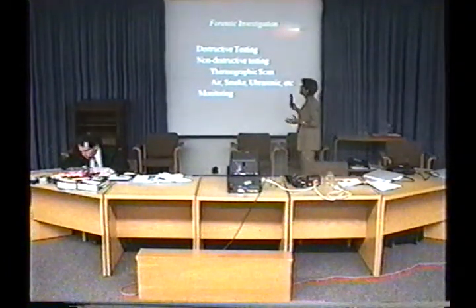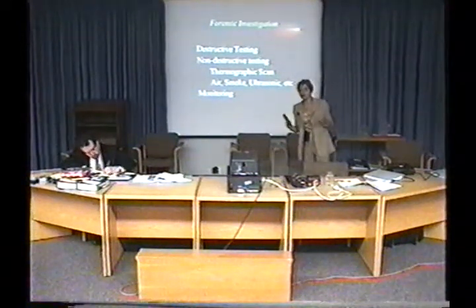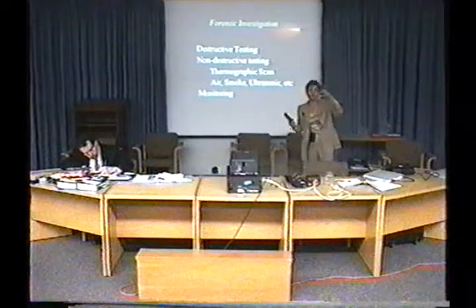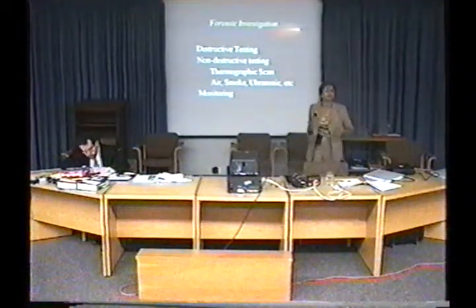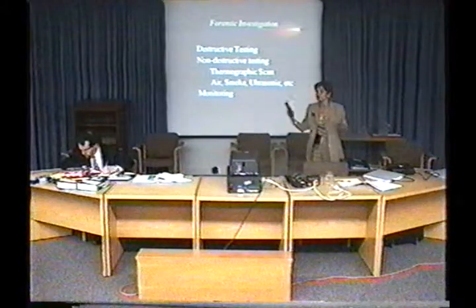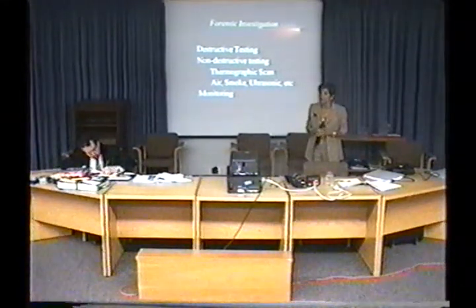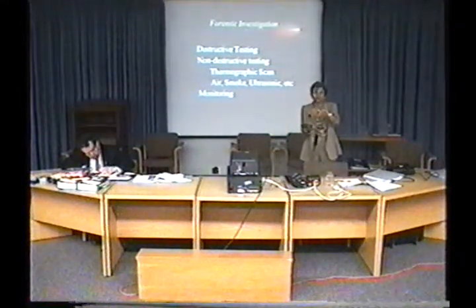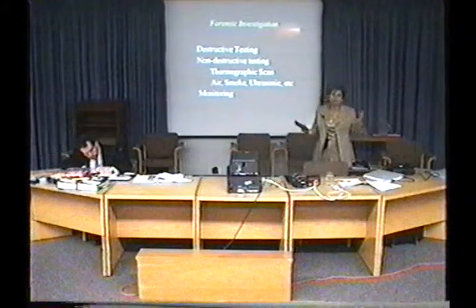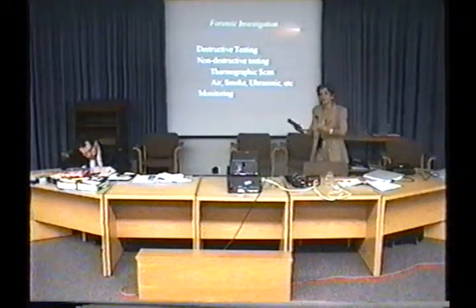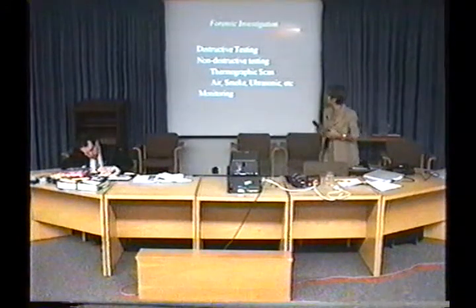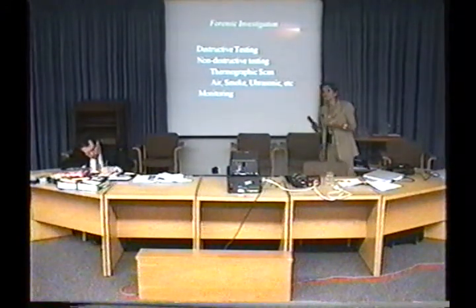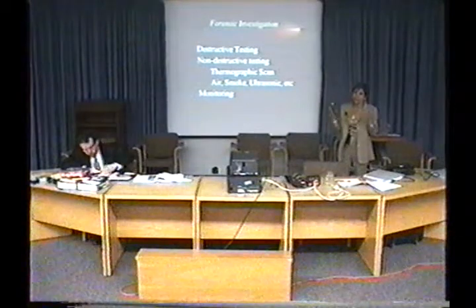The first step is destructive testing, which is if you have a concrete slab, you can take a core sample. You drill it and you remove it, take it to the lab, you test it, you find out what is the compressive strength of that core. You can find what type of salt is in it, what type of chemical you have in it, cement ratio and water ratios, is there air in it.